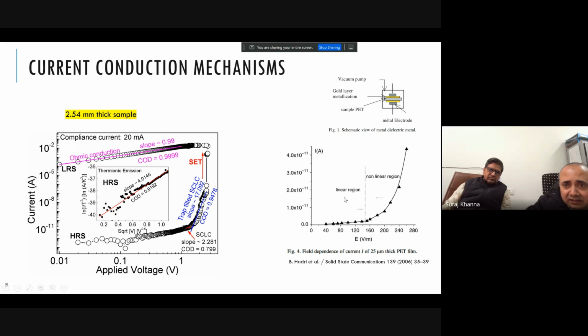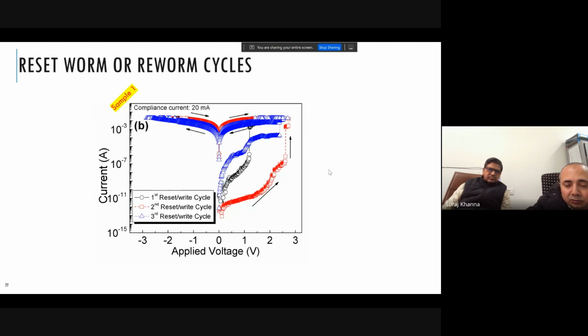Okay. So this gives the historical evidence that some other groups in the past have also tried to work with PET, not in the yarn form, but as a thin film, where they've grown a thin film of PET in between two gold electrodes, and they have also seen that as the field across the electrodes increases, you can see a sharp increase in the current across the PET. So that basically supports our finding. Here we have more than one cycle of the device being run, and every time it shows similar behavior where it goes from a highly resistive state to an ohmic state.